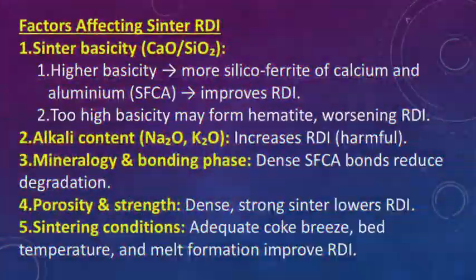Factors affecting sinter RDI. Firstly, sinter basicity, CaO by SiO2. Higher basicity means more silicoferrite of calcium and aluminium, SFCA, which improves RDI. Too high basicity may form hematite, worsening RDI. Alkali content, Na2O, K2O, increases RDI, harmful. Mineralogy and bonding phase, dense SFCA bonds reduce degradation.